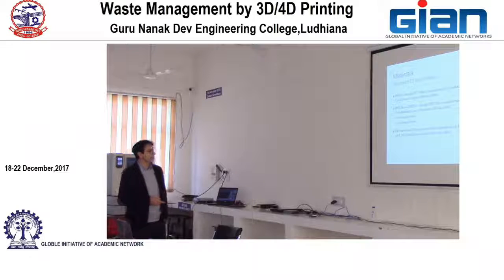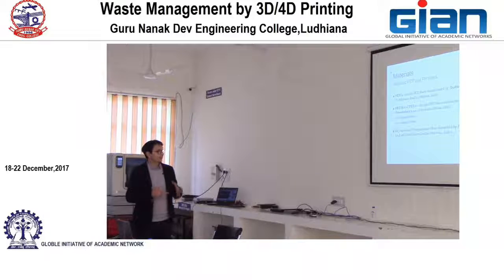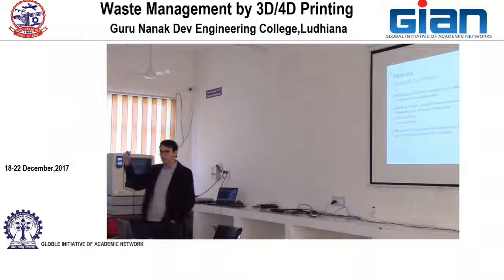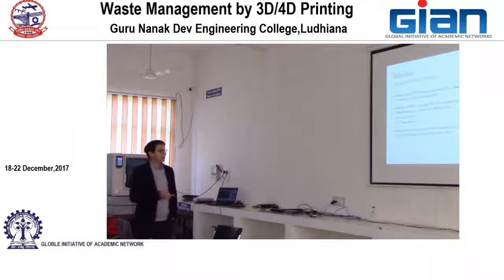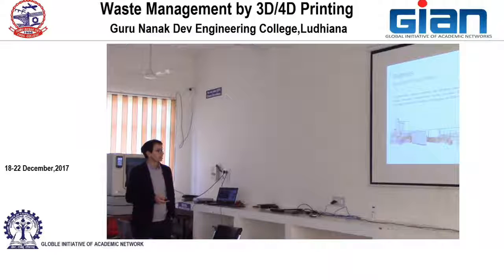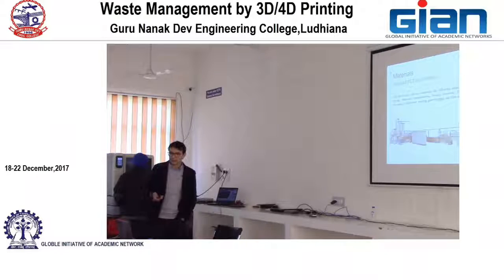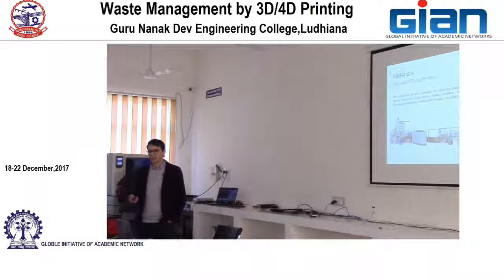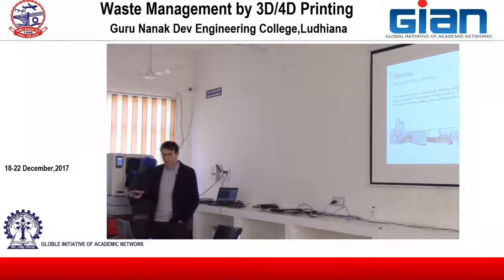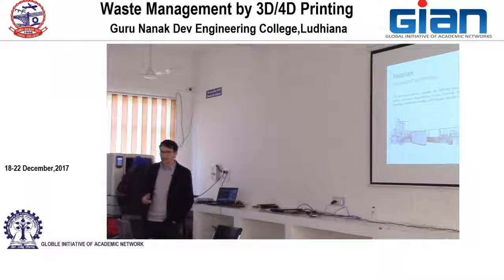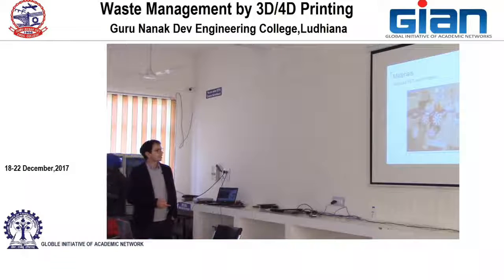And the PET fibers that we examined were of different kinds. We examined straight fibers, also crimped fibers or embossed fibers. All those fibers were obtained by changing the die of the extruder that processed the PET flakes. This is the extrusion line that we used in the plants of industrial companies in northern Italy, which are in the business of extrusion of plastic filaments from virgin or recycled material. So those are parts of the extrusion line.